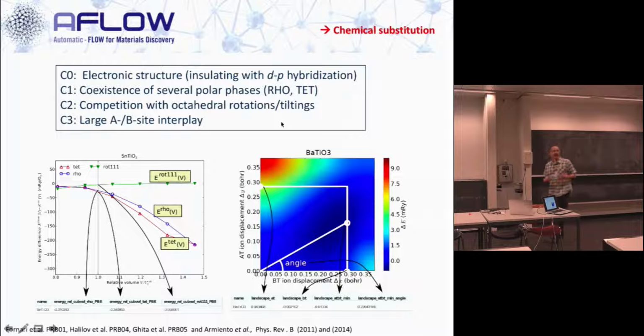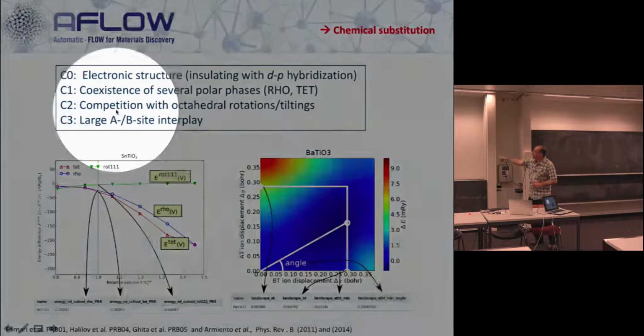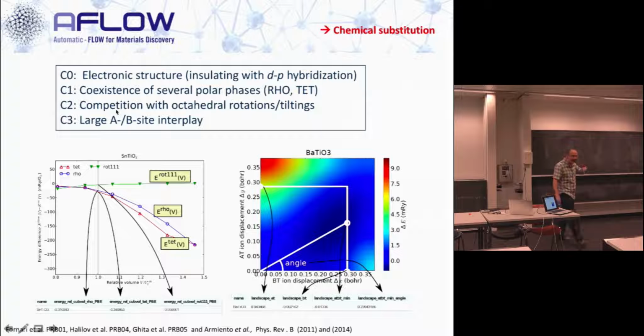And then we need to have a large piezoelectric effect, meaning that when the polarization, the distortion, is rotating from the 1-1-1 direction to the 0-0-1 direction, there is a strong coupling with the cell, so that the cell actually gets deformed and we can have a large piezoelectric response. Okay, so these were qualitative. This was done to understand what's going on in PZT. And so we need to translate those concepts into something numerical that we can put in a database, right?